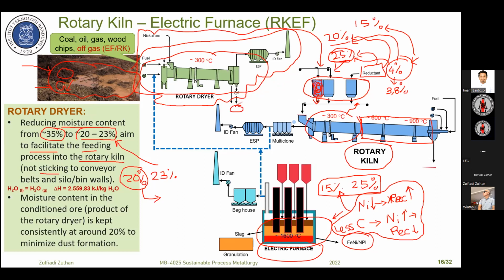We should also control the moisture content in the dry ore, because the aim is to reduce the moisture content in the ore in order to make it easy to feed to the kiln and also to get stable products. And also the moisture content in the ore should be kept around 20% in order to minimize the dust formation. For sure, if we reduce the moisture to 0%, the dust formation will be high, maybe more than 20% or 30%. If we keep the moisture content around 20%, the dust formation from the rotary dryer is around 1 to 2%, which is the common value.